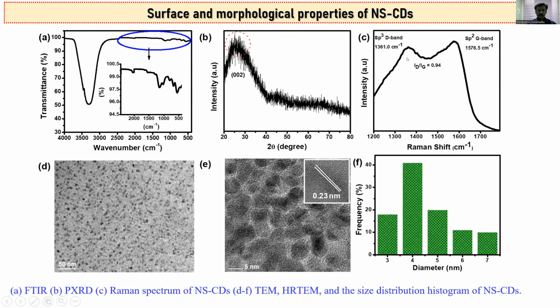We can call it the sp2 and the sp3 hybridization. Both bands were accompanied by the vibration of sp2 and sp3 carbon atoms in hexagonal and two-dimensional terminal phases. This also happens in graphitic disorder carbon dots. The relative intensities of both D and G bands were found to be at a maximum average of 0.94, which also indicates the well-arranged graphitic carbon nature of these carbon dots.